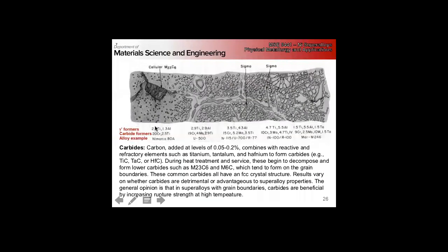We do have unwanted phases that show up - some carbides. Carbides can be either detrimental or advantageous. If we are in a superalloy with grain boundaries, the carbides are going to be beneficial, giving us an increase in rupture strength.